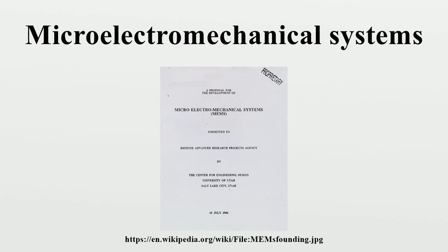Ceramics. The nitrides of silicon, aluminium and titanium, as well as silicon carbide and other ceramics, are increasingly applied in MEMS fabrication due to advantageous combinations of material properties. AlN crystallizes in the wurtzite structure and thus shows pyroelectric and piezoelectric properties, enabling sensors, for instance, with sensitivity to normal and shear forces. TiN, on the other hand, exhibits a high electrical conductivity and large elastic modulus, allowing to realize electrostatic MEMS actuation schemes with ultra-thin membranes. Moreover, the high resistance of TiN against biocorrosion qualifies the material for applications in biogenic environments and in biosensors.